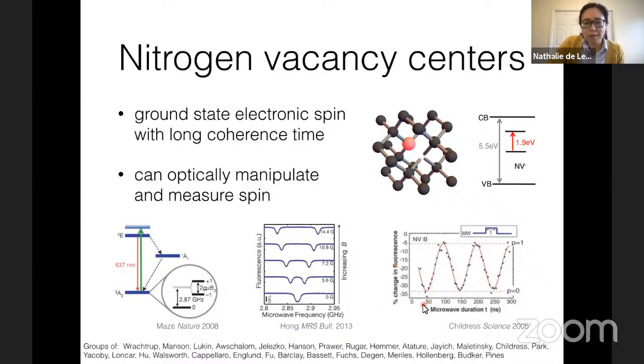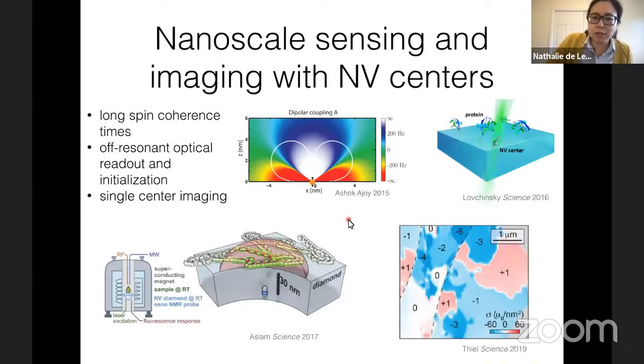People have shown that you can coherently manipulate and measure the spin. And basically this set of special characteristics, the long spin coherence time at room temperature and the optical readout, has really spurred work among dozens of groups around the world looking at this one color center in diamond. One of the things that people are particularly excited about is that you can use these as nanoscale sensors. You have long spin coherence times at room temperature and a really convenient method of readout and initialization. Then you take the many decades of work that people have done in figuring out how to do magnetic resonance and apply sophisticated pulse sequences, and combine that with the work over the last three decades or so on single center imaging. The really exciting prospect is that you have this point sensor that you can read out, and you can use it to look at the local environment.